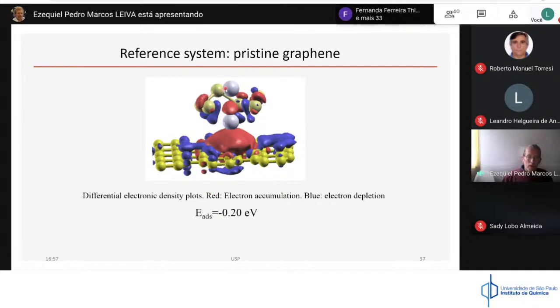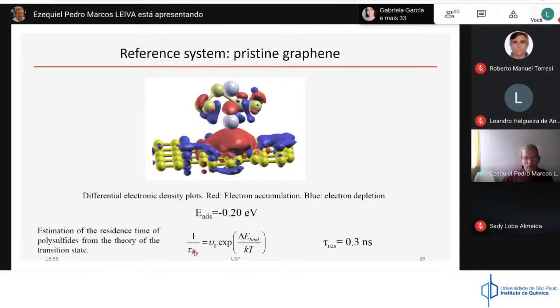If you put a polysulfide molecule interacting with the surface, you get an energy of minus 0.2, which perhaps doesn't tell much to you, but it's easy to estimate the time that a polysulfide would remain on the surface depending on this energy. You can make an estimation by using transition state theory. Transition state theory tells you that the rate, that is the reciprocal of the time, is a prefactor, a frequency factor, multiplied by an exponential of the activation energy that you must pay to take this polysulfide away from the surface. If you use transition state theory, you will find that with an interaction energy of minus 0.2, the time that this polysulfide remains trapped on the surface is about 0.3 nanoseconds. That means this number is very small. It's too small to retain the polysulfide for a long time.